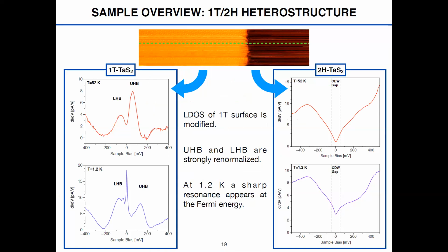While in the 2H case, we do see what is expected, so there's nothing new. At both 52 Kelvin and 1.2 Kelvin, you see this charge density wave pseudogap. It is the expected one and the one reported in literature.